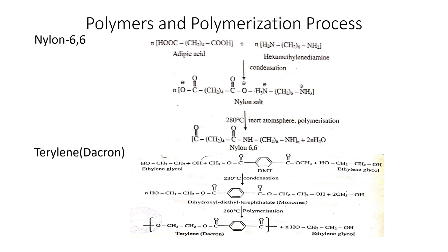The polyester chips are formed when the monomer is heated in vacuum at 260 to 300 degrees Celsius to form terylene polymer by polymerization. The polyester chips are dried and then fed into a hopper. Then they are passed into melting vessels and forced through a spinneret.